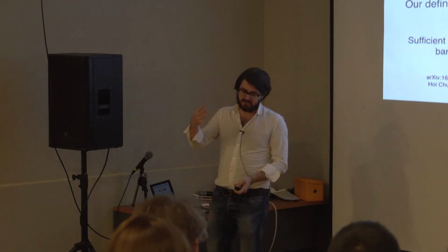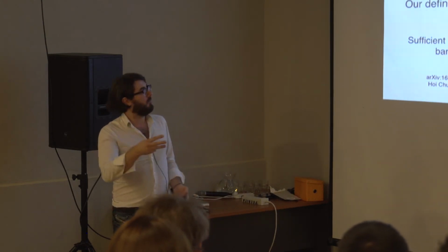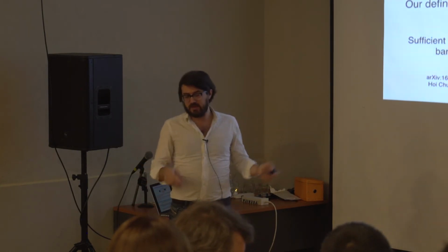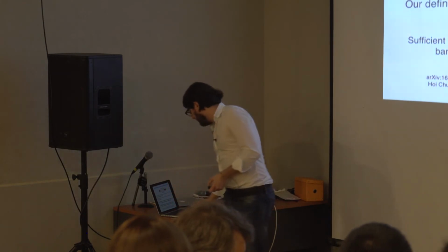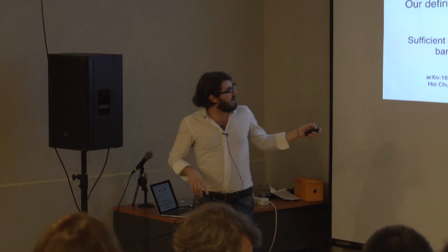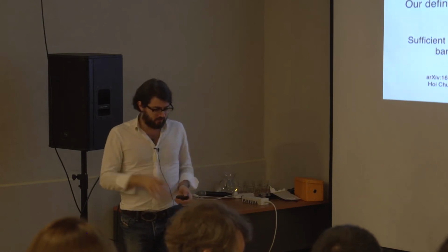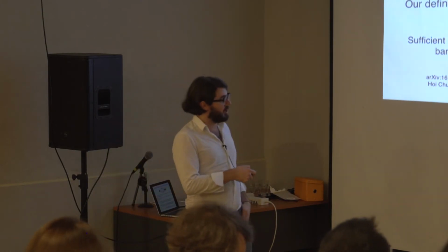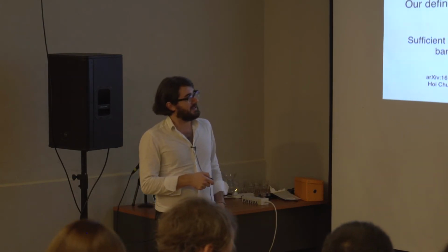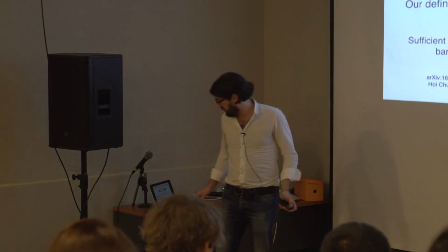So elementary band representations are important in two ways. If they describe an atomic limit, they're connected. If they're disconnected, they describe topological bands. So there's a corollary to this in terms of checking for materials. A sufficient but not necessary condition of topology is that the eigenvalues or the characters of a set of bands do not match those of some of the band representations.